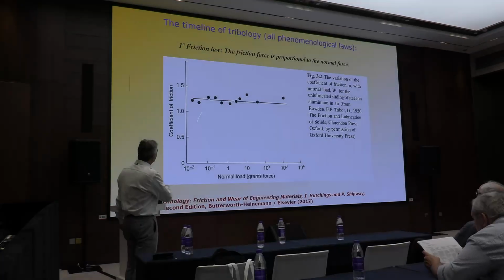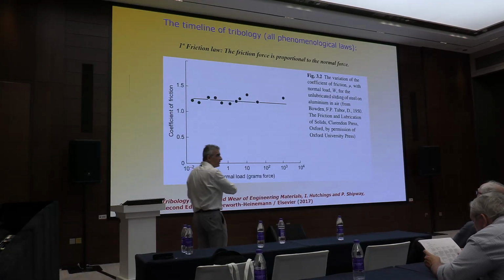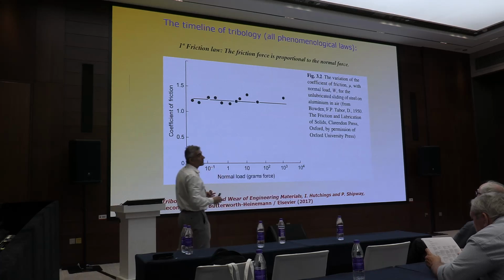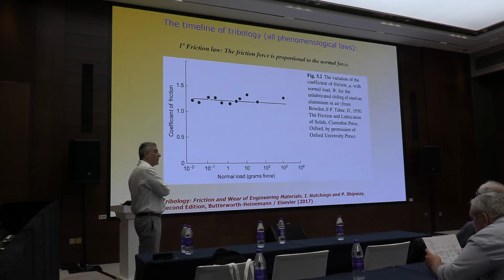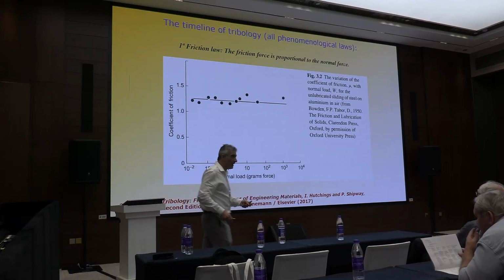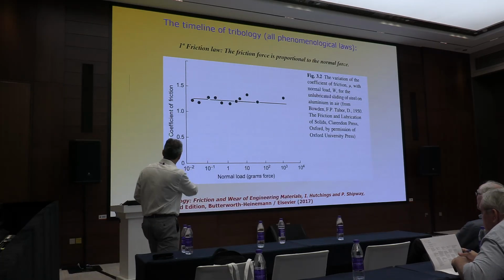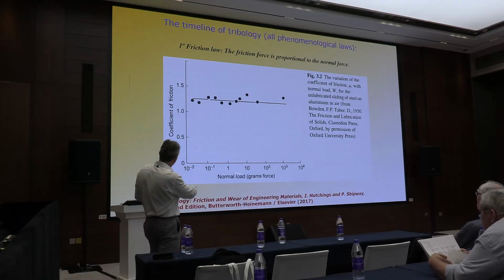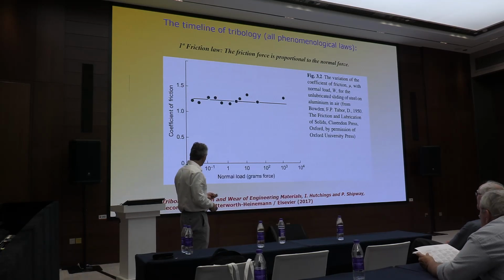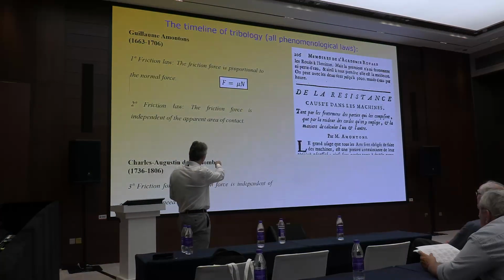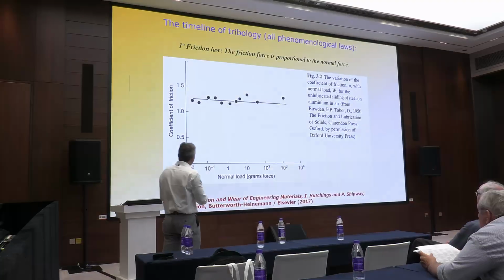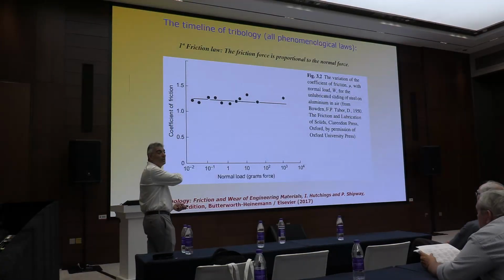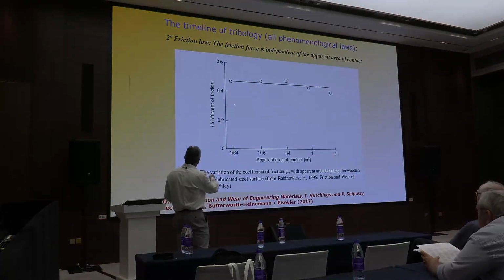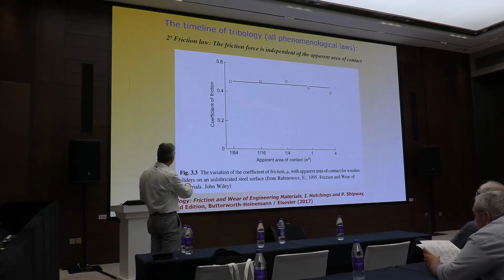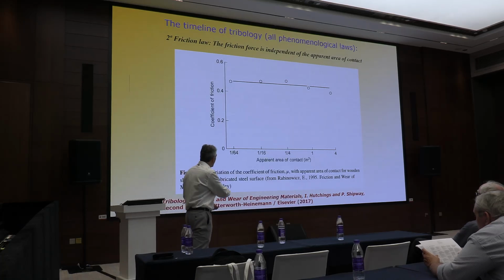Well, here you can see some experiments. After that, you will see different figures with the verification of the laws and against the laws. For example, this is verification because the coefficient of friction is linear, it's independent of the normal load. This here is independent of the normal load. Okay, this is in agreement with Amontons' law. In this case, this is the second law: the coefficient of friction is independent of the apparent area of contact. Okay, it's in agreement with the second law.